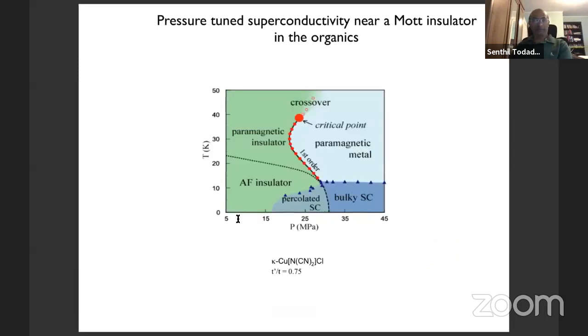Now, these organics can be easily tuned with pressure. So when you tune pressure, in one example, one example of a class of examples within this family of materials, you go from an antiferromagnetic Mott insulator to a Mott transition to a metal which at low temperatures is a superconductor. Okay, so this again is an example of superconductivity in the vicinity of the Mott transition.